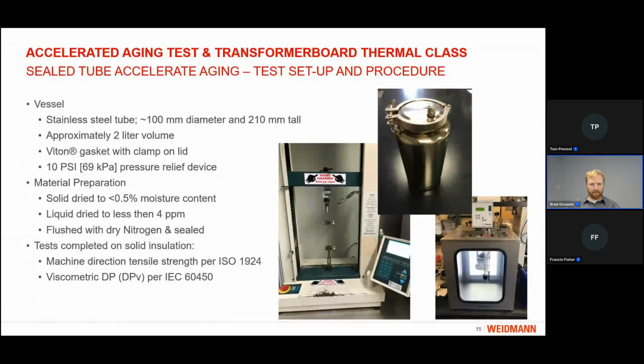With the material preparation, all solid materials, both pressboard and paper, are dried to a moisture content of less than 0.5%. And the liquid is dried using heat and vacuum to a moisture content of less than 4 parts per million. During the filling process of these vessels, after combining the solid and liquid components, the headspace is then flushed with dry nitrogen prior to being fitted with the cover and sealed.